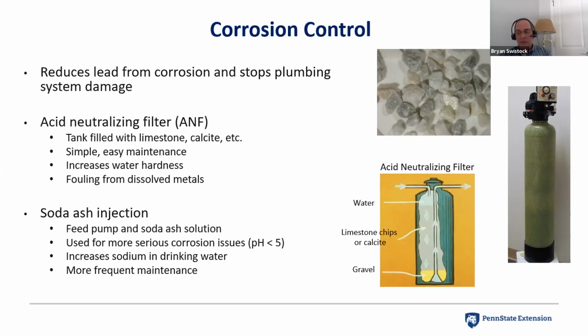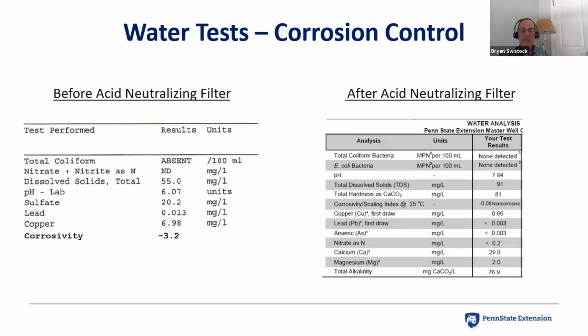The acid neutralizing filter, people I've talked to that have had both of these would definitely say that the acid neutralizing filter is a much preferable route to go if it'll work for you. And this is a typical situation of what you see when you install an acid neutralizing filter. The before filter is on the left, and we notice a pH of 6.07, and we have a corrosivity index of negative 3.2, so very corrosive water. We've got almost 7 milligrams per liter of copper in the first draw, and we've got 13 parts per billion of lead. So a pretty significantly corrosive water.